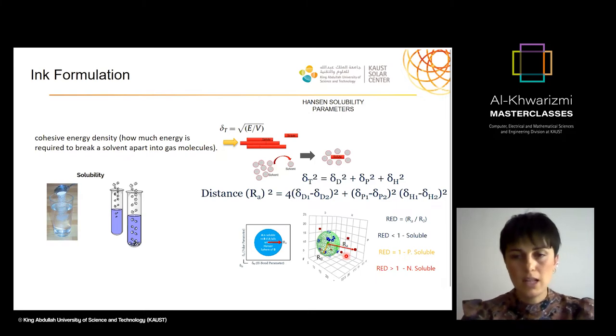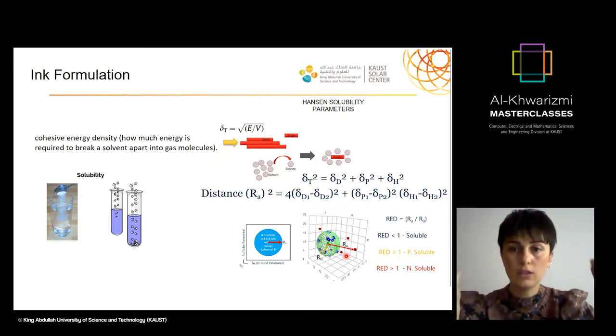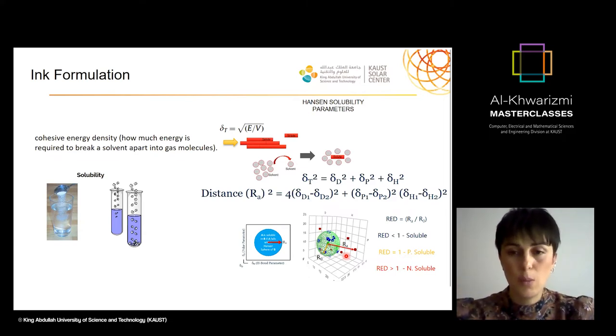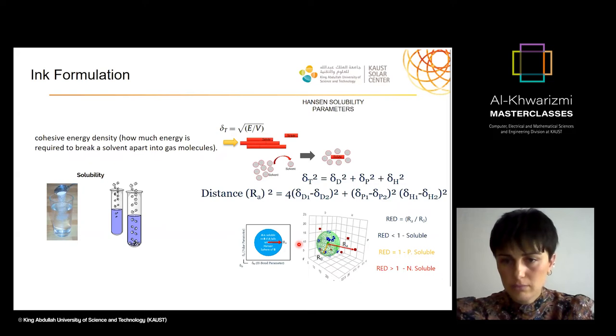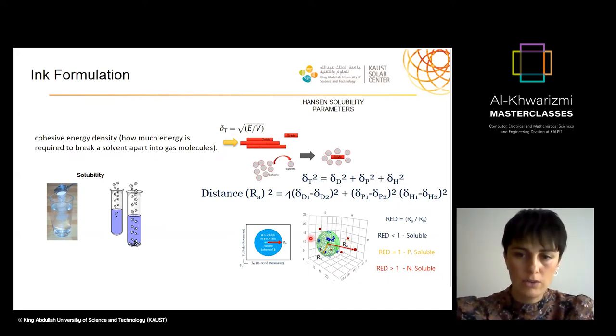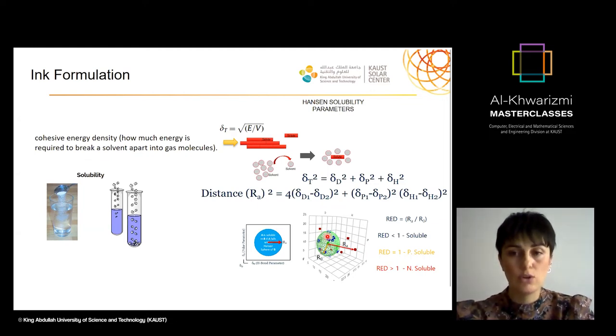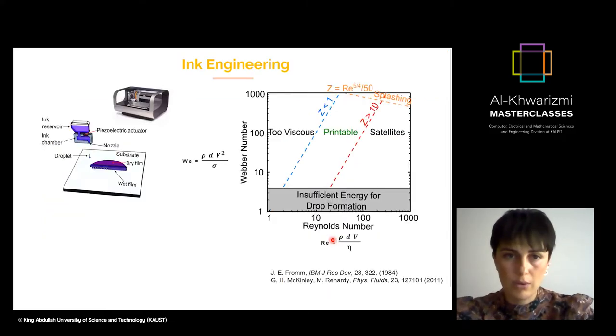I'm not going into detail, however, there are several different ways that you can bring two non-solvents into a soluble form, which I find fascinating because it is the linear regression of these two. So if you have a point here and on the other side of the sphere, you can combine these two and then bring the combination within the sphere of your solubility. So this is how we predict initially for the solubility parameters of our materials.